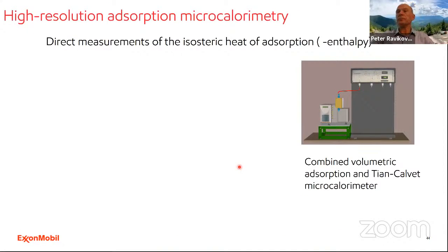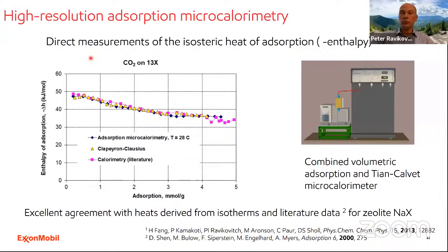In the calorimetry, we do a simultaneous adsorption and microcalorimetry experiment when we measure the adsorption isotherm, but with dosing into the calorimetric cell. In the Tian-Calvet type microcalorimeter, you have 2 cells, one with the sample, another one without sample, and these cells have an array of thermocouples, and you're measuring directly the heat of adsorption. So it's a direct measurement. So when we do it on CO2 on 13X, we compare here 3 different results. One is our calorimetry.